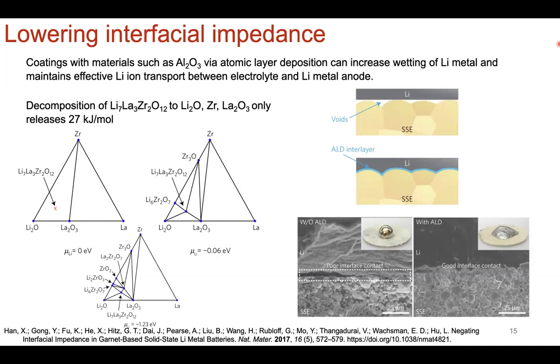And so by depositing alumina onto the garnet system, lithium wets it much better. Now, the only issue with this type of engineering, of course, is that you have to think about the decomposition products. So alumina is good, but it can also impede ion migration. We saw that with the cathode type material, where coating with, let's say, niobates or alumina helps with chemical stability, but can also impede ionic conductivity.